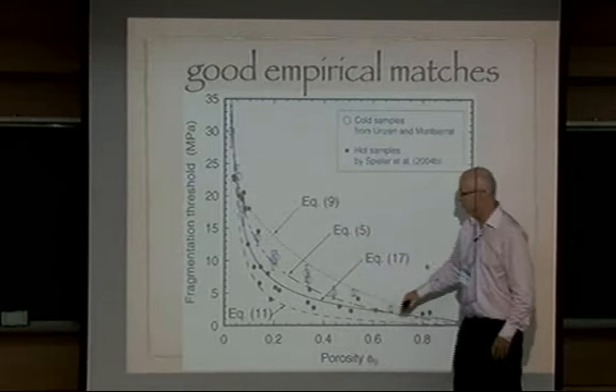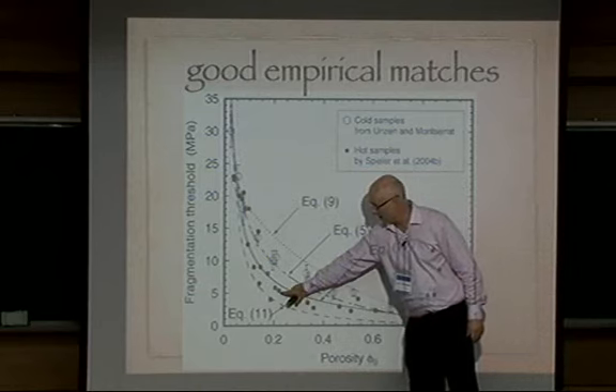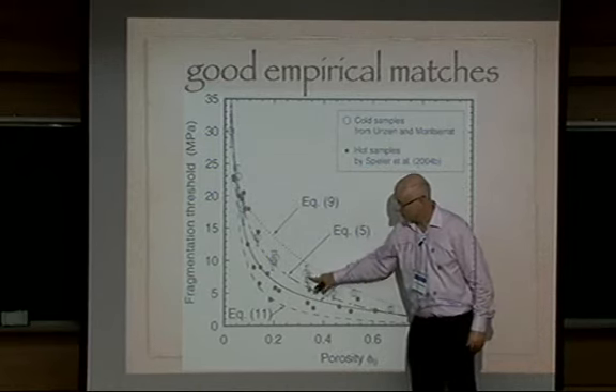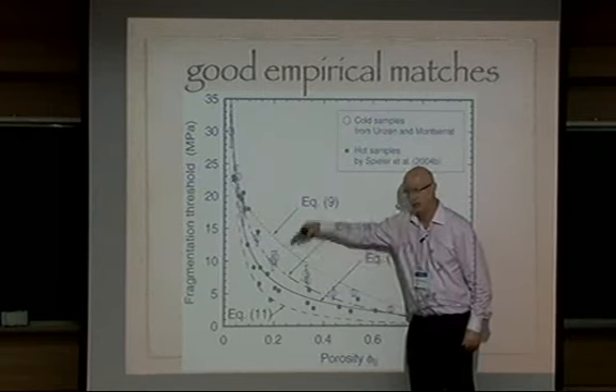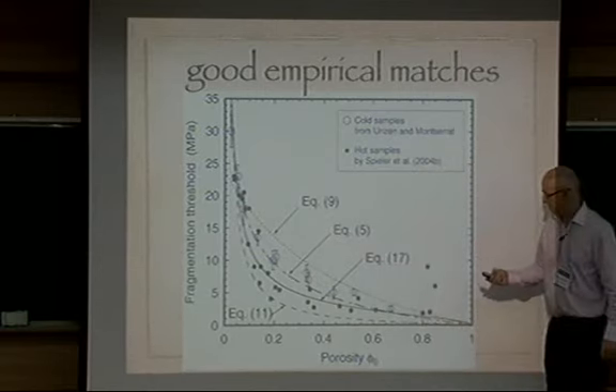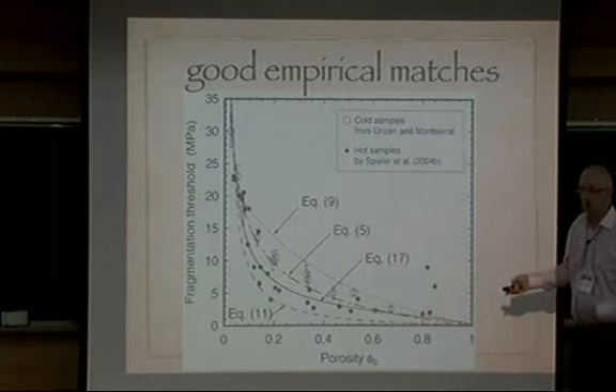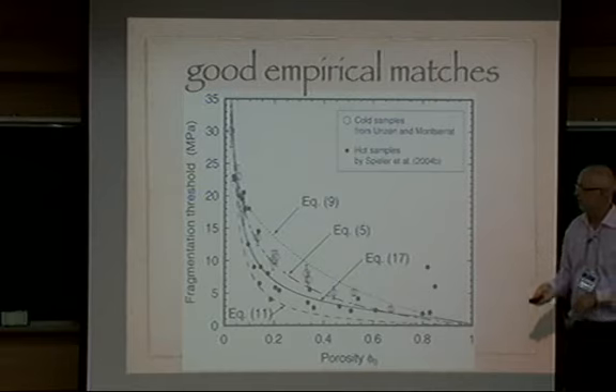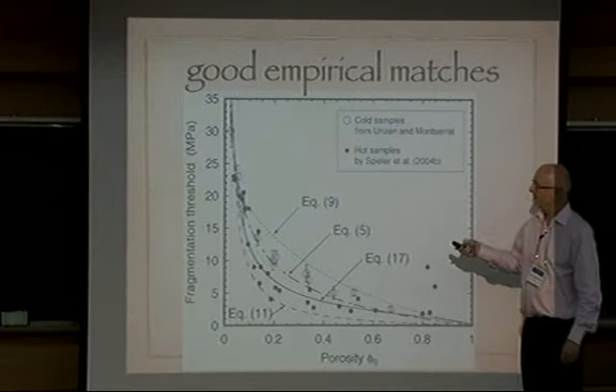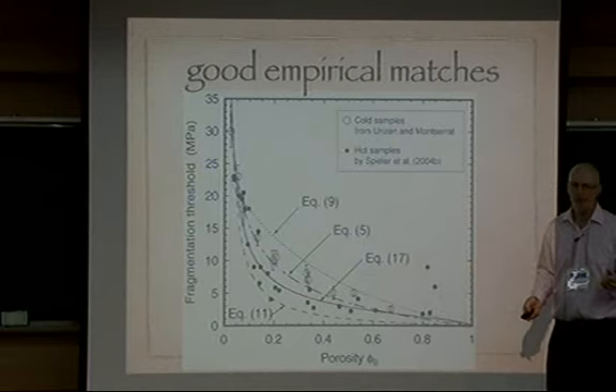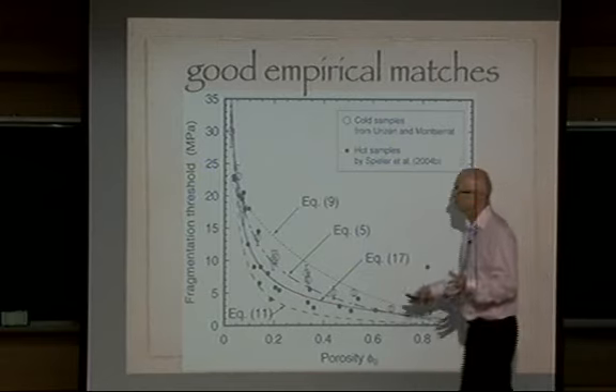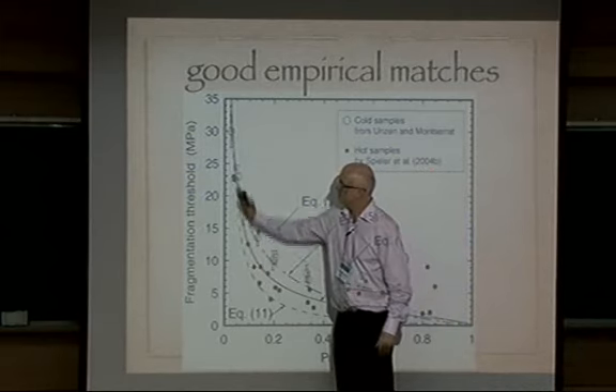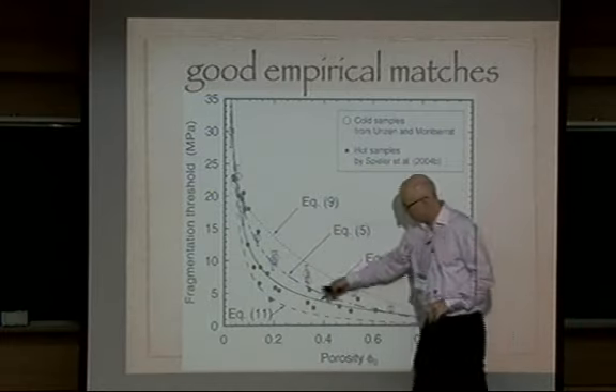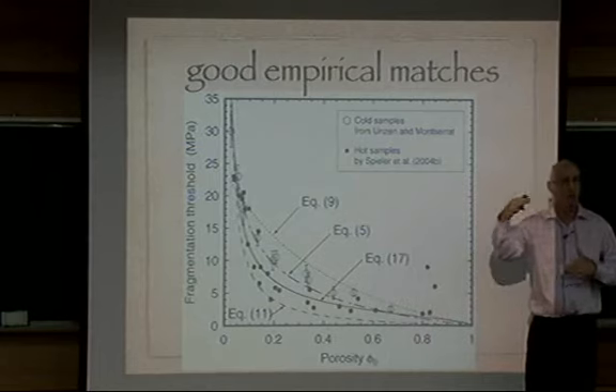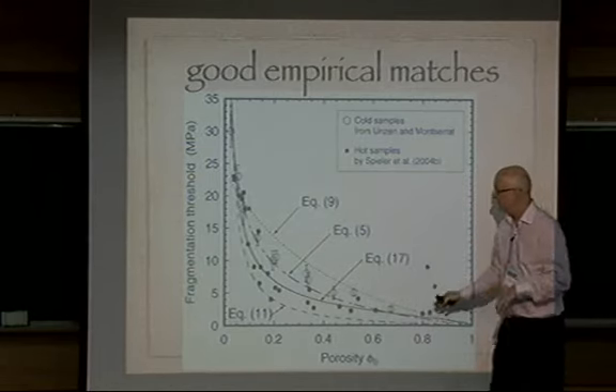The dots are hot and cold samples. The hot samples are these solid dots. The open symbols are cold samples. A whole variety of experiments were done here. The different lines going through come from various approaches to shock tube theory. They all do fine and give you this sort of behaviour. But that's partly because they're also empirical. They've said, we can see that pressure goes to infinity as phi goes to 0, so we'll put a 1 over phi in there. And it goes to 0 as phi goes to 1, so we'll multiply by 1 minus phi as well. So it's a little bit empirical.